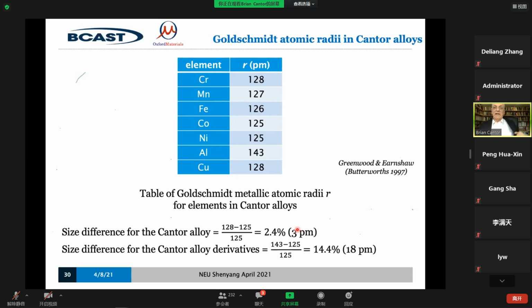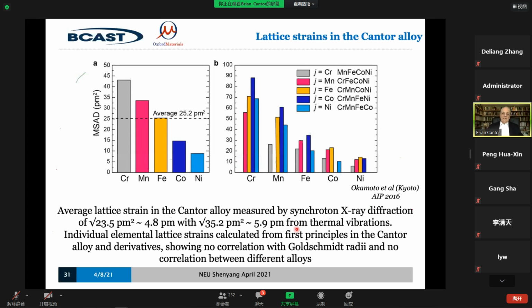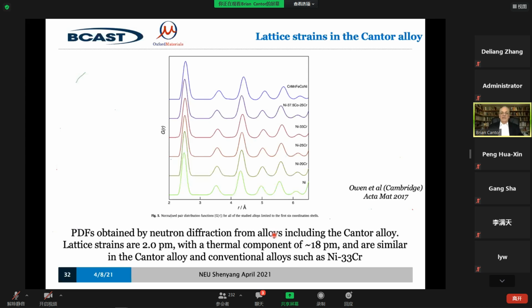Now, is that a reasonable estimate? Well, yes, it is. The synchrotron X-ray diffraction experiments show 4.8 picometers as the actual lattice strain. And neutron diffraction from the Cantor alloy shows typical lattice strains of 2 picometers. So 3 is not bad. The Goldschmidt radius is a very crude estimate, but it's not bad. Well, what's the effect of that?